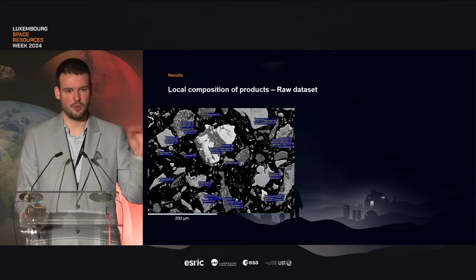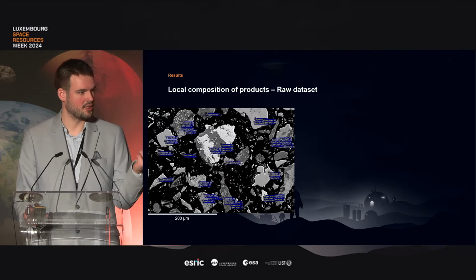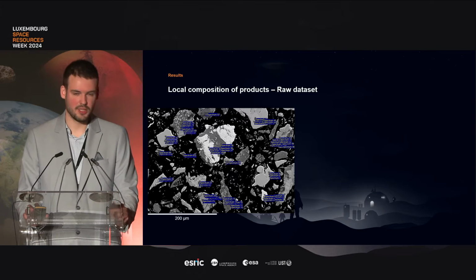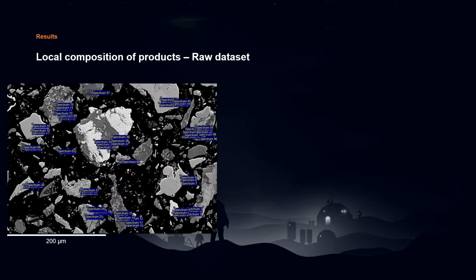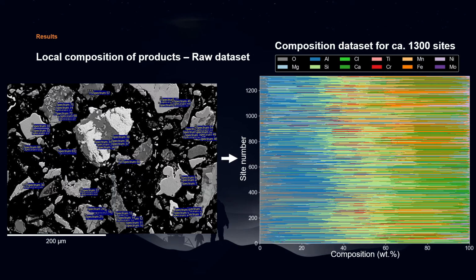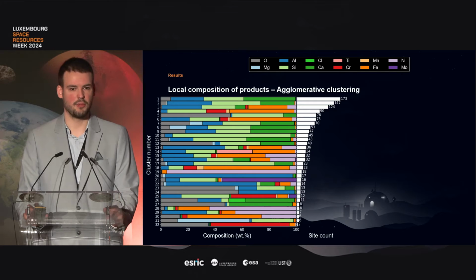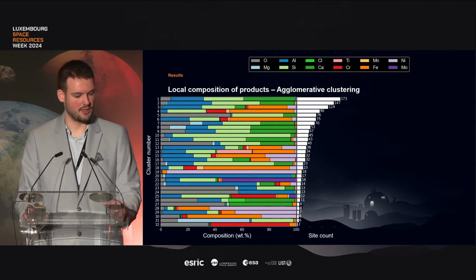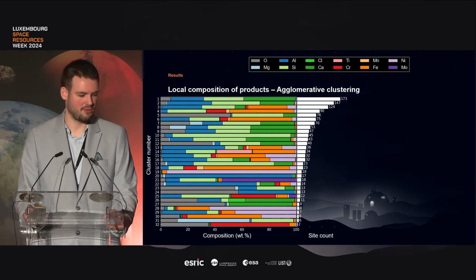So this was what we had for the global composition, but now we want to look point by point at what the actual particles, the actual product, looks like. So this is what we did. Here we have, for all those points, a corresponding spectrum and a corresponding composition, which gives us a slightly more complicated data set. So here we have about 1,300 points. To make sense of that, we need to order it and coalesce it into a simpler data set. What we did for that is clustering, agglomerative clustering. So we ran an algorithm across it, and we reduced it down to 32 recurring compositions that here are ordered by counts, by number of appearances.